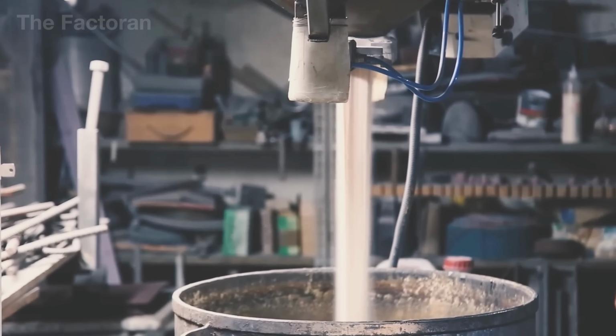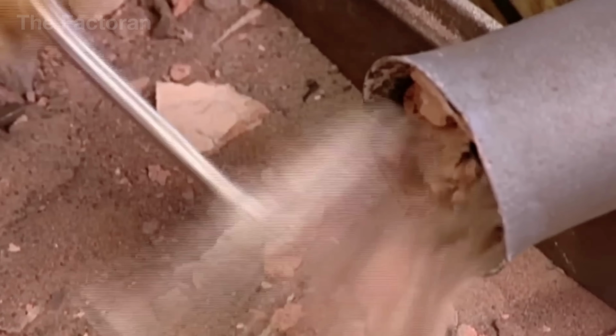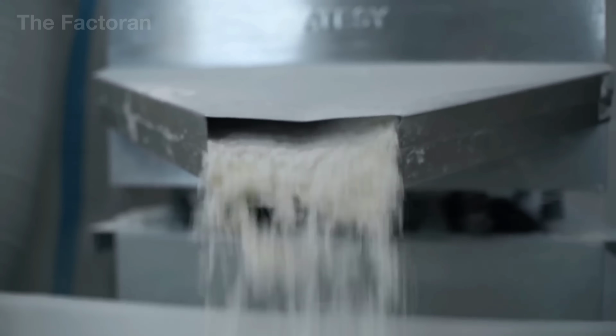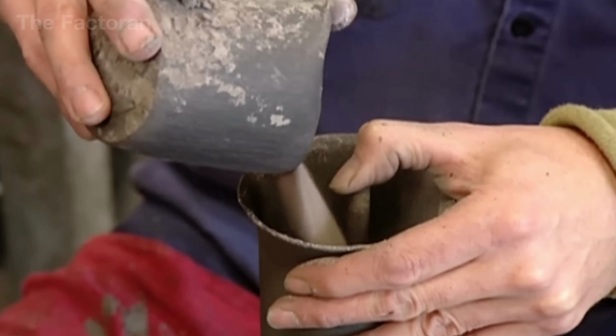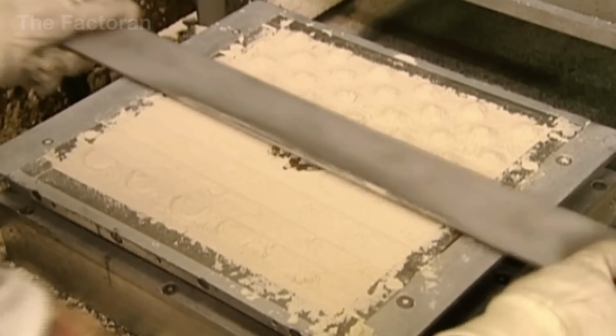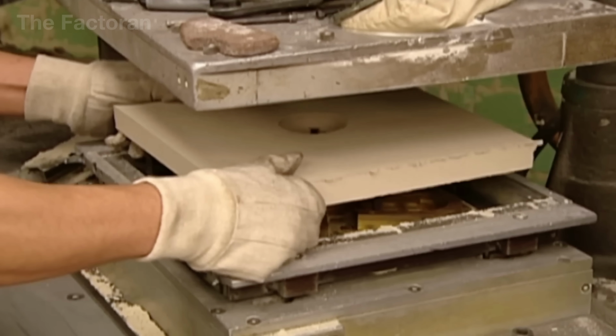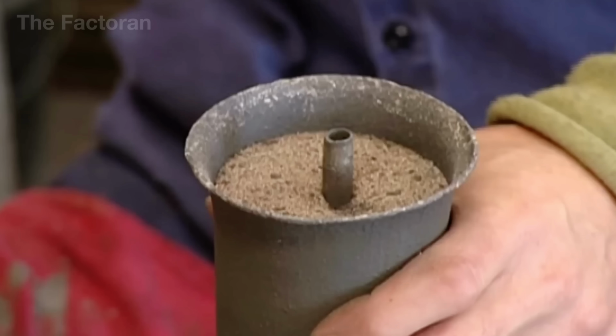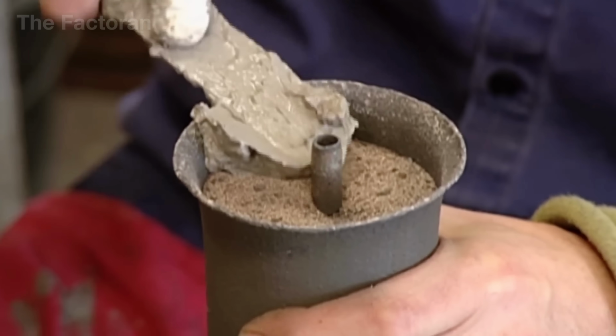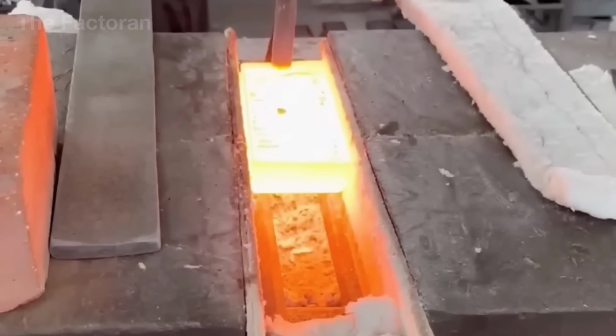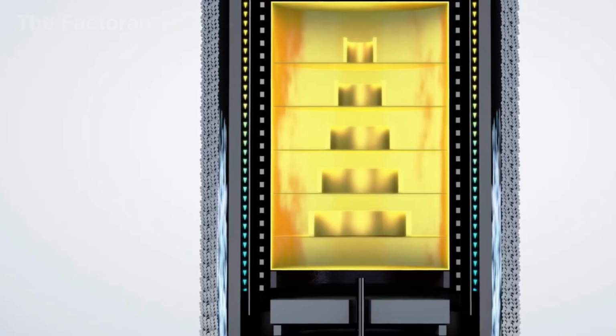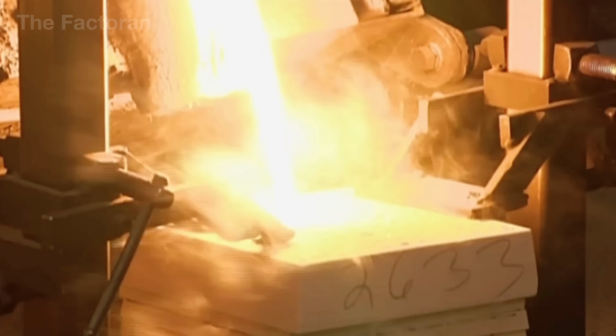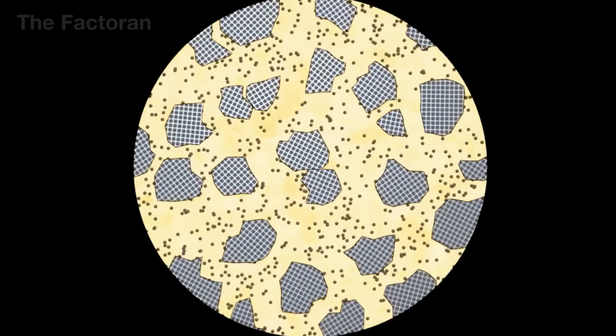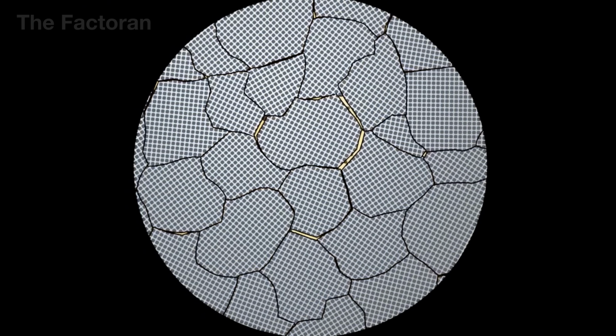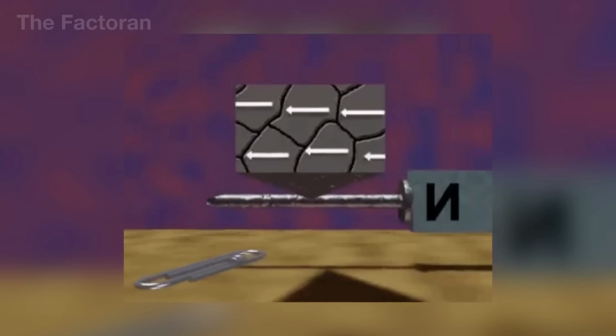After the neodymium, iron, and boron alloy has been refined, it is ground into an ultra-fine powder inside an inert gas environment to prevent oxidation. The resulting mixture appears dark gray with a subtle violet tint, and its particles measure only a few microns across. This magnetic powder is then placed into a high-pressure steel mold while being exposed to a powerful magnetic field reaching several Teslas. Within this field, millions of microscopic alloy particles begin to rotate and align in the same magnetic direction, much like countless compass needles all pointing toward a single pole.